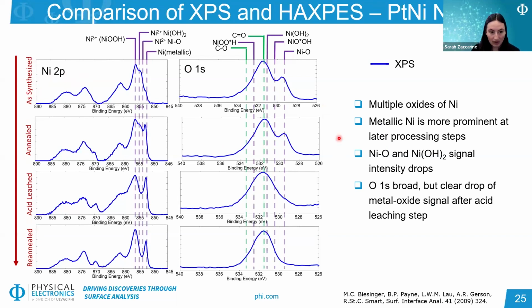And there's a few different nickel oxides that are likely present here. We see a small nickel metallic shoulder potentially, but this grows clearly after these different post-processing treatment steps. And we also see some of these nickel oxides decrease with especially acid leaching and reannealing conditions. In the oxygen data, we also see these changes in nickel oxide, especially after acid leaching, we kind of lose this metal oxide shoulder. And we also see in these green lines the indication of a couple different organic species that are present at the surface as well.